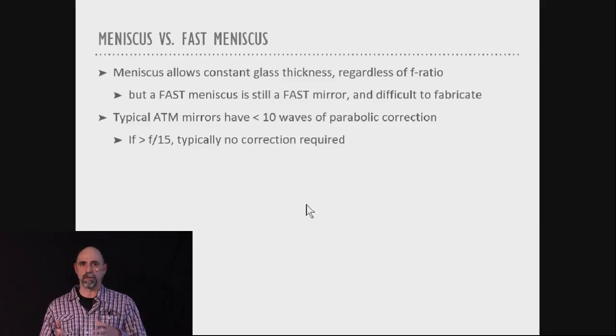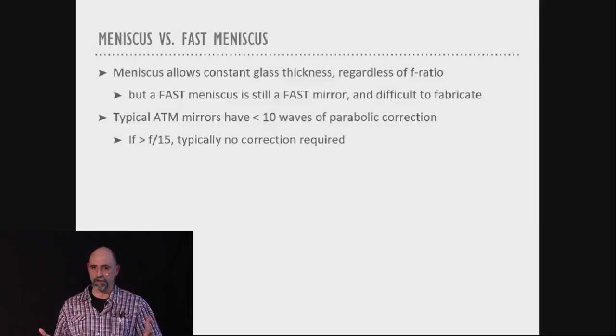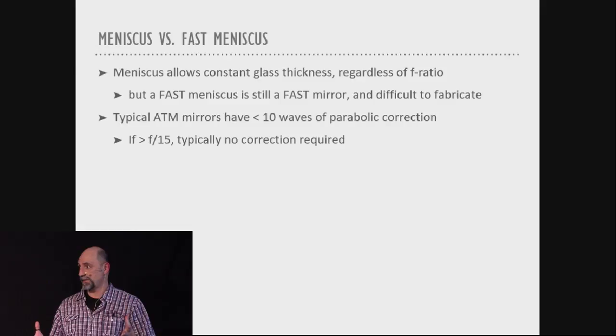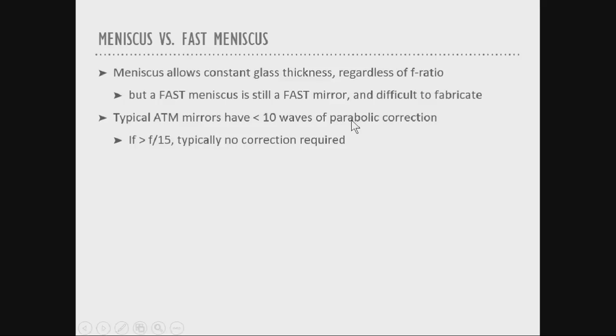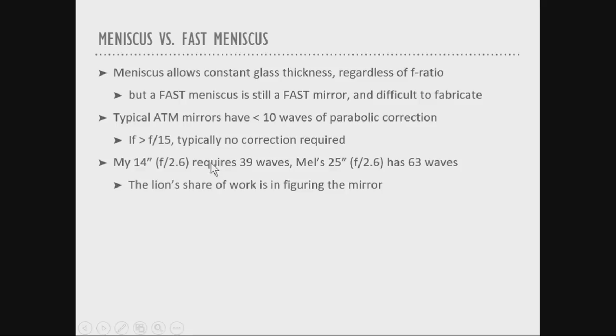Typically, when you're making a mirror on your own, you start by creating a spherical shape, and then you parabolize it. The delta in going from the spherical mirror to the parabola is usually measured in waves of green light. Typically the correction you have to put into a sphere to make it parabolic is less than 10 waves for a typical ATM mirror. And if you're over, say, f/15, you typically just work with a spherical mirror. You don't put any correction in at all. My f/2.6 requires 39 waves of correction, and the 25-inch of Mel Bartels has 63 waves of correction.